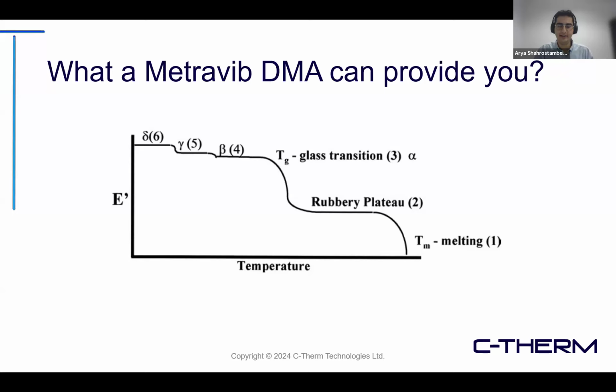For example, beta here is the side chain movements, and all the other local movements or stretching of the chains of the polymer. So these are very neat properties of the material. However, it is very important to note that neither TMA or DSC or any other instrument is sensitive enough to pick up those transitions, and it is only DMA that is capable of measuring and picking up those points and those transitions. Another important part here is that, in order to reach those transitions, you need to go to extremely low temperatures.